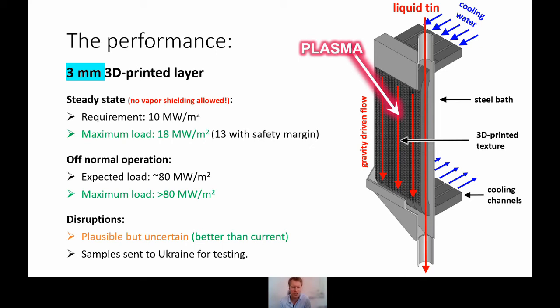I should say also there is some uncertainty here, so that's why I've just put more than 80 megawatt per square meter instead of an actual number, because you need very good estimates of the actual energy dissipated per evaporated particle, this kind of thing. And for disruptions, actually, there's no difference, because for disruptions, only the top tenths of a millimeter of the CPS play a role, because the pulse is so incredibly short that the heat doesn't really penetrate much further. All right.